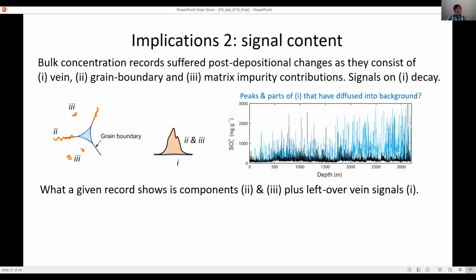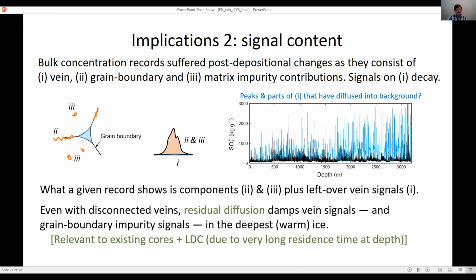Or if climatic signals on entry to the top part of the core quickly segregate to grain boundaries or crystal matrix away from the veins, then not much can be lost. But I really don't know the partitioning. Yes, even if the veins are blocked, residual diffusion will damp signals, though, at depth where the ice is warm. And in fact, the residual diffusion, because it involves grain boundary motion, will also damp grain boundary impurity signals, component 2 there. And I think this may be interesting.